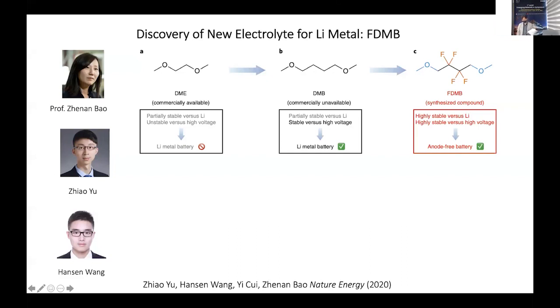DME is an ether solvent used in the existing electrolyte for lithium metal. It has reasonable stability versus lithium, but it gets oxidized by the cathode, so it's not stable. It's very challenging to use for real lithium metal batteries. Then you can increase this middle hydrocarbon chain from 2 to 4. It becomes DMB, that's in the middle. Stability becomes better, but still not stable enough. Adding fluorine to the central part of DMB, it becomes FDMB. And it turned out this is a new molecule. It didn't exist before, and Zhao did the synthesis of this molecule. We use that for the solvent.